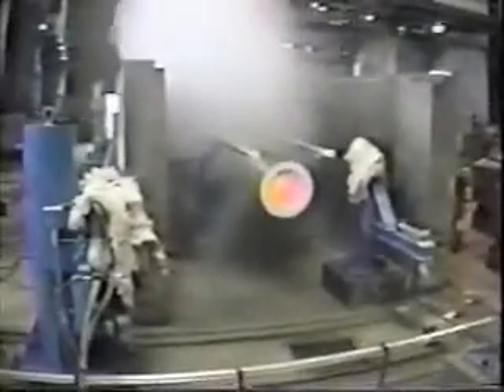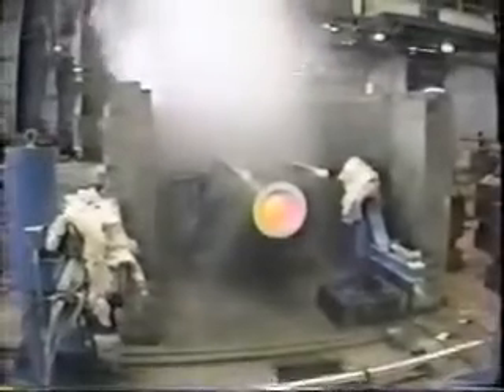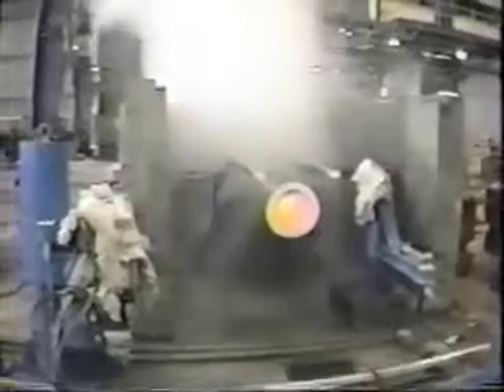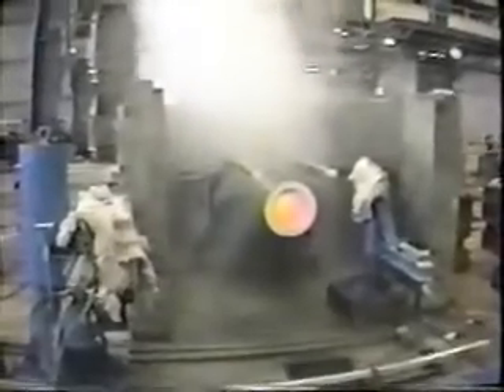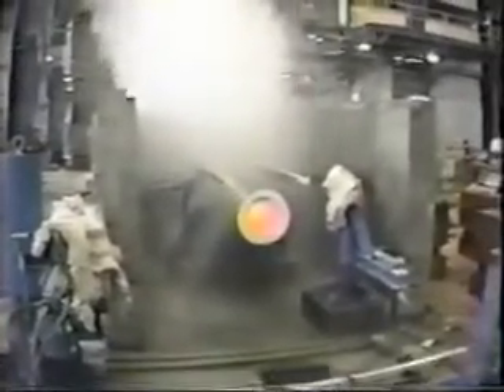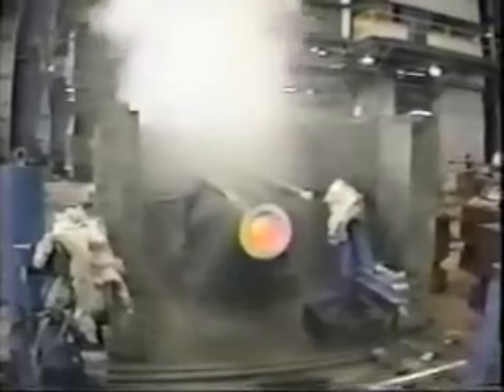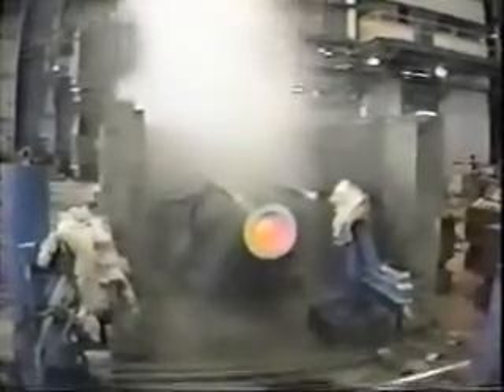The water is turned on within about 15 seconds after pouring when the metal is properly in place in the mold. The cooling water cycle is different for different castings and is important to the proper quality of the casting when extracted.